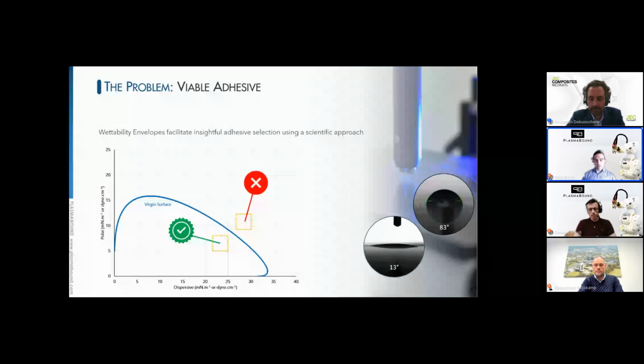However, there may not exist, and this is a very important point in the design phase, an adhesive that falls within the wettability envelope and has the suitable properties to meet the in-service needs of the product. So essentially, if it needs a high tensile strength or some property that no adhesive inside the envelope can achieve, well, that's where pre-treatment or surface preparations come from. So we would look to a surface preparation to improve the surface energy or energy available on the surface, and expand the wettability envelope so that it can work on the adhesive outside the envelope. And now the adhesive is likely to bond to the prepared surface and make it a viable option going forward.